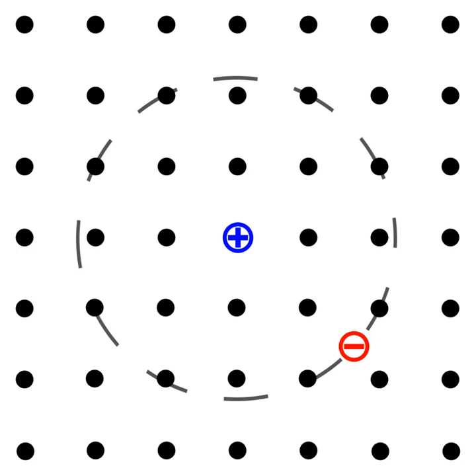In single-wall carbon nanotubes, excitons have both Wannier-Mott and Frenkel character. This is due to the nature of the Coulomb interaction between electrons and holes in one dimension. The dielectric function of the nanotube itself is large enough to allow for the spatial extent of the wave function to extend over a few to several nanometers along the tube axis, while poor screening in the vacuum or dielectric environment outside of the nanotube allows for large 0.4 to 1.0 electron volt binding energies.